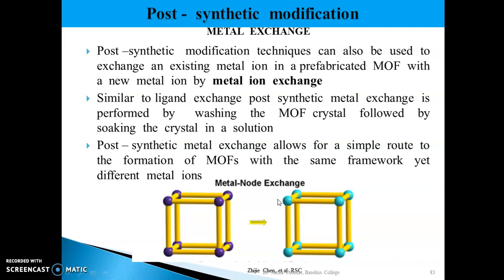Okay. So, post-synthetic modification techniques can also be used to exchange an existing metal ion in a prefabricated, already synthesized MOF with a new metal ion by a metal ion exchange process. Similar to ligand exchange, post-synthetic metal exchange is performed by washing the MOF crystal followed by soaking the crystal in a new solution that contains a new metal ion. Post-synthetic metal exchange allows for a simple route to the formation of metal organic frameworks with the same framework yet different metal ions. So, we are retaining the framework structure.